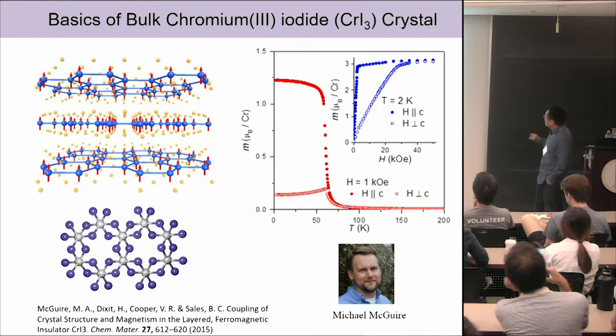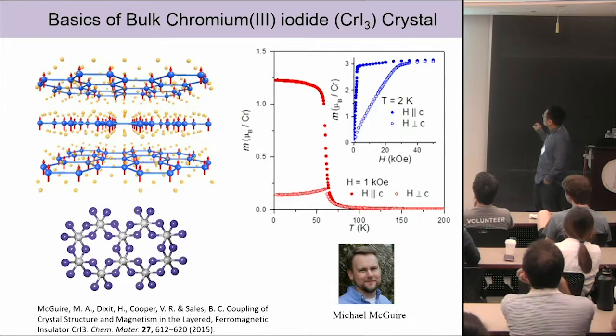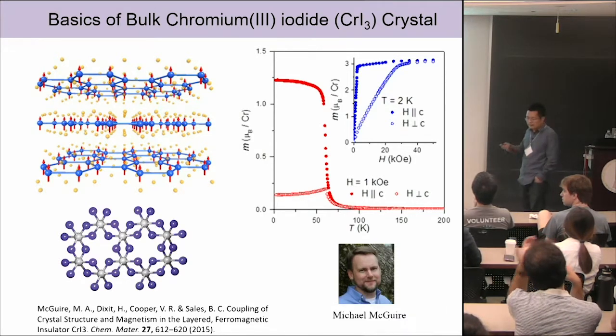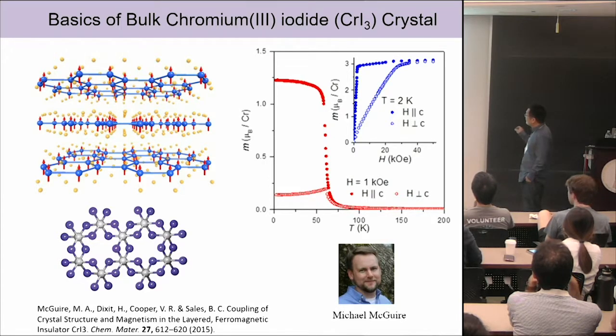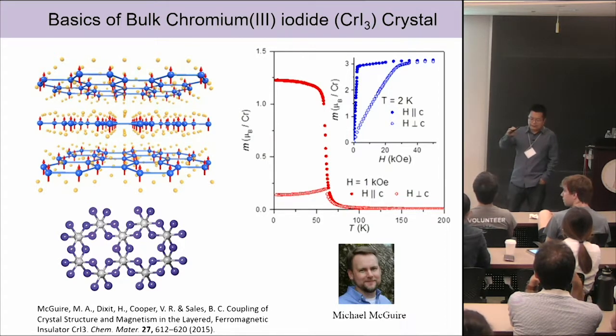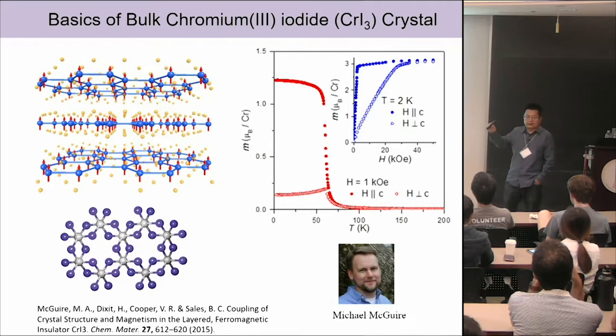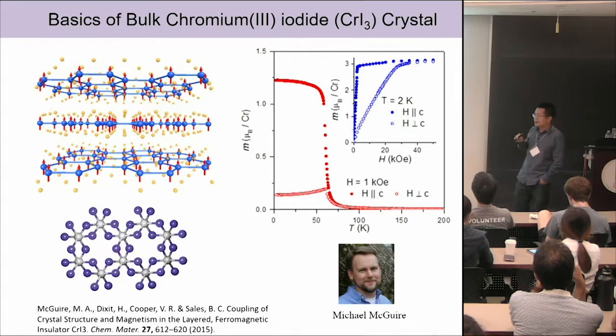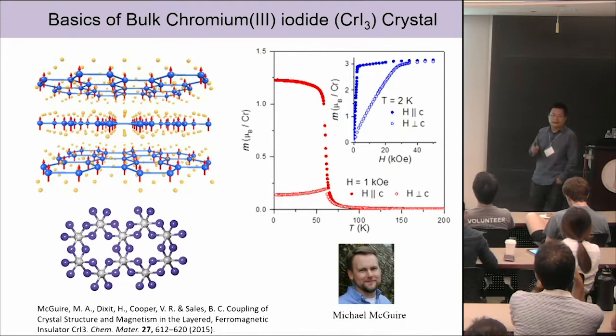My collaborator, Michael McGuire, when he told me about this chromium triiodide, what got me really interested is that he showed from his measurements that this particular crystal has very strong out-of-plane anisotropy. This is very important because, as we all know, as you thin down the crystals, there's the Mermin-Wagner theory. It says if the Heisenberg exchange interaction is isotropic, then there's no long-range order in the 2D or lower dimensional limit, right? So we need anisotropy. And what he showed is there's very strong out-of-plane anisotropy, with spins pointing out of plane. This is good news, right?